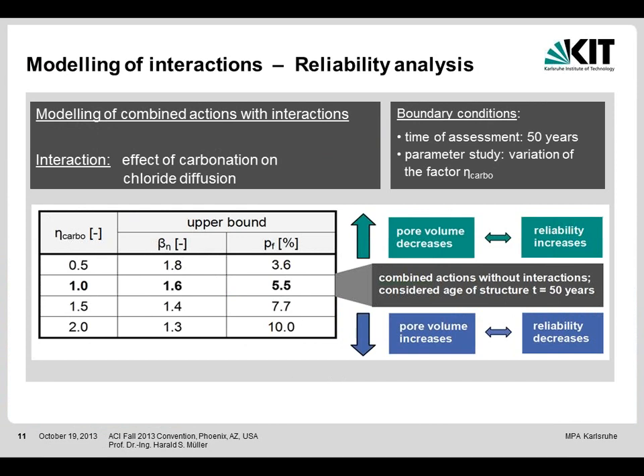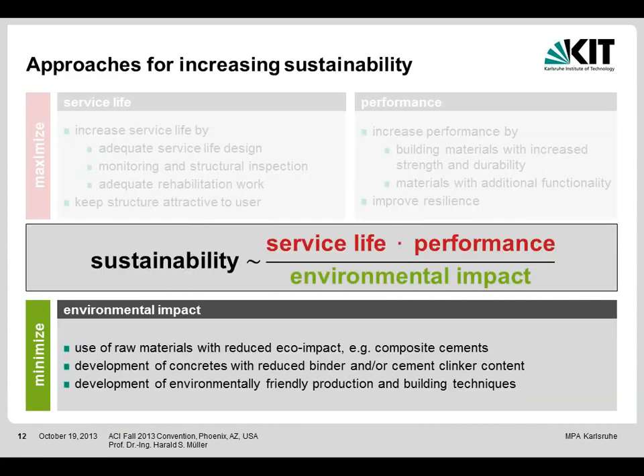Now, if we, for example, have a lower value of eta carbo, we have a decreased pore volume, which leads to a lower failure probability and a higher reliability index. It is vice versa if this factor increases. This means we have to determine this factor very exactly, and the differences are rather large. So I could go more into detail, but I have some other subjects, so I'll switch to the next one.